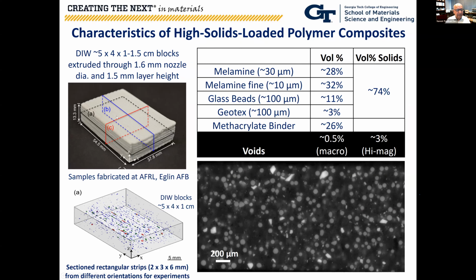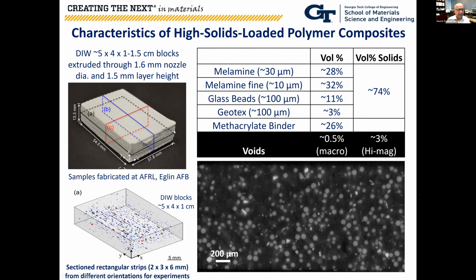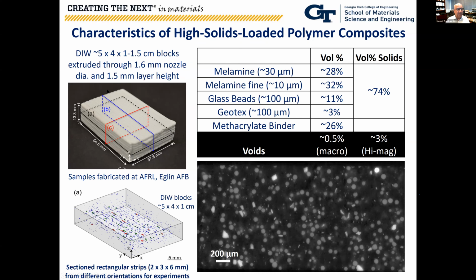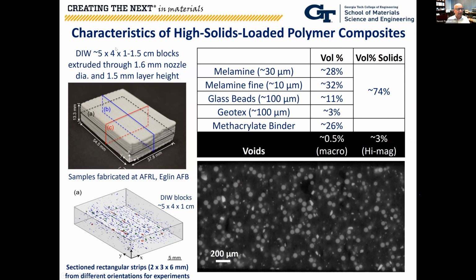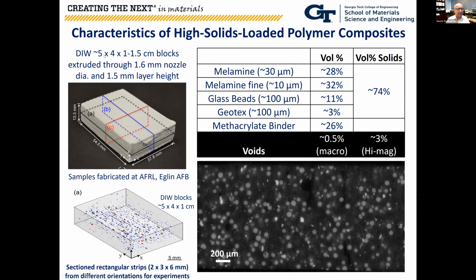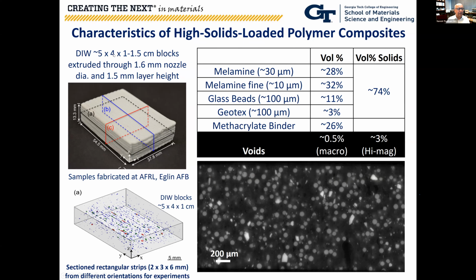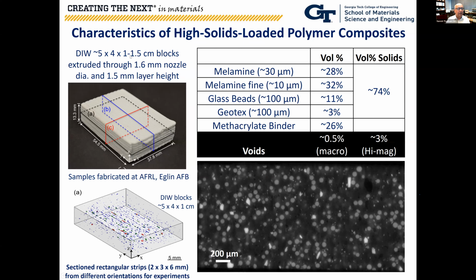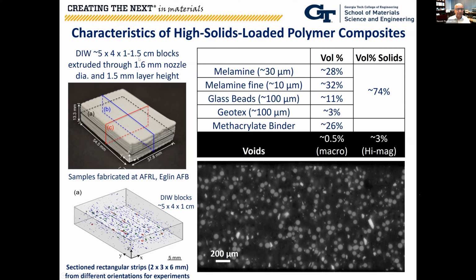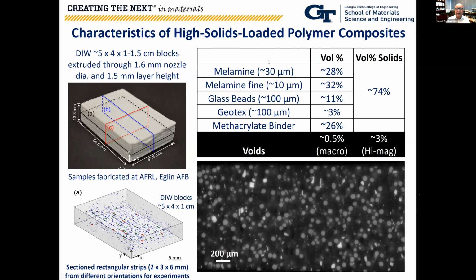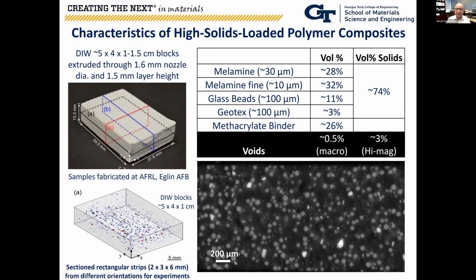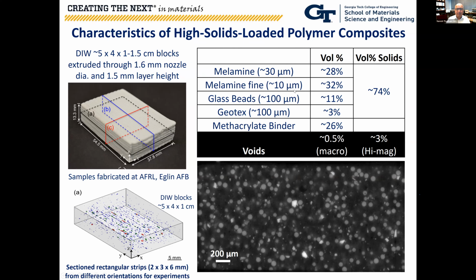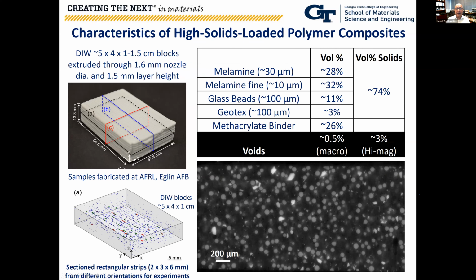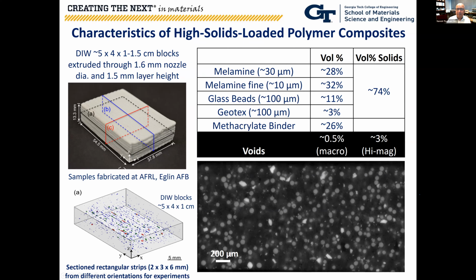The specific material that we studied was fabricated in the form of these rectangular cubes, about 5 centimeter by 4 centimeter by about 1 to 1.5 centimeter thickness. These contain two different types of melamine particles, 30 micron and 10 micron, and they also contain glass beads that are about 100 micron.